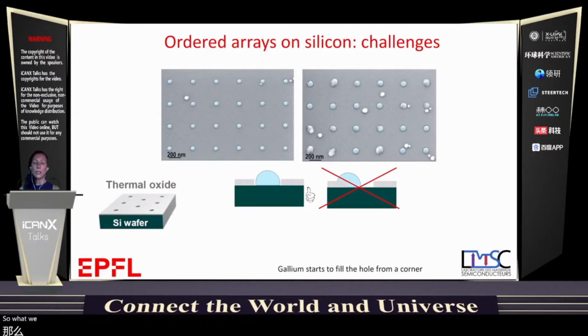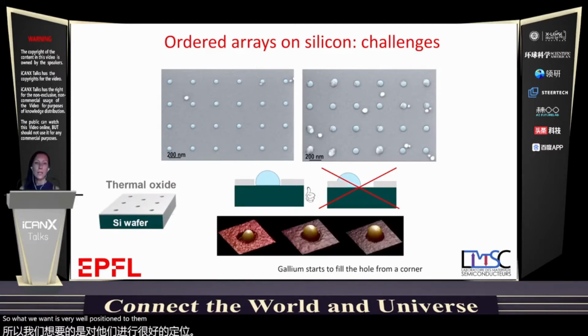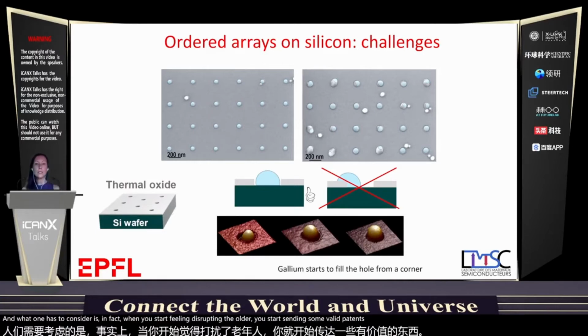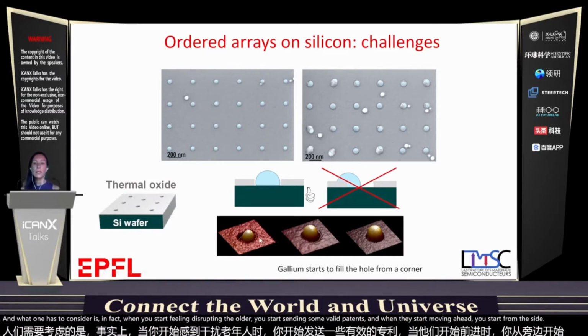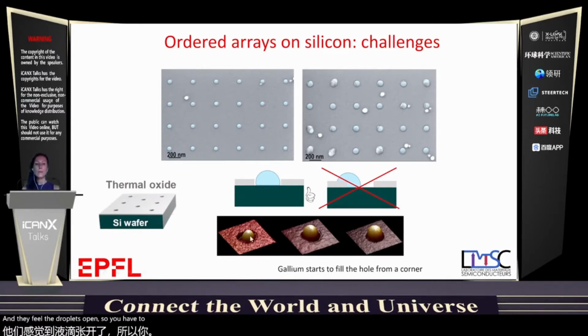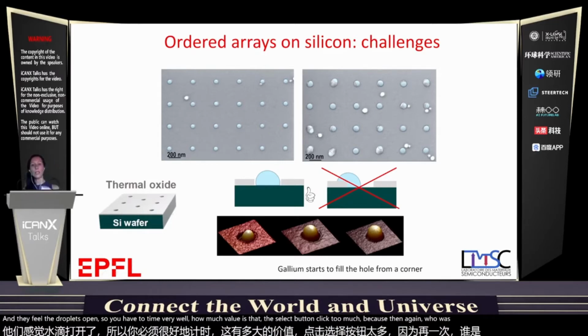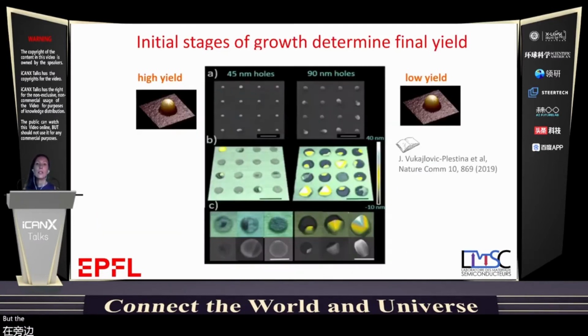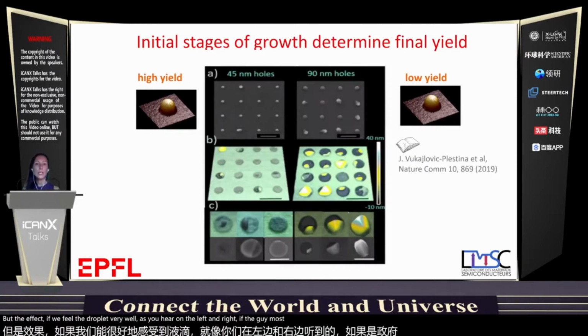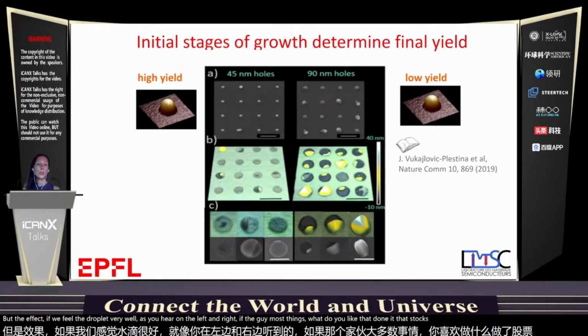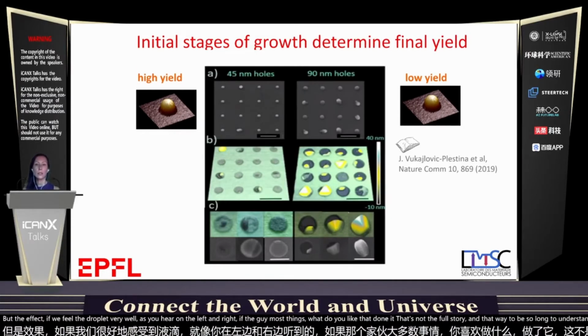So what we want is a very well positioned droplet. And what one has to consider is, when you start creating this droplet in the hole, you start sending some gallium atoms, and when they start growing, they start from the side, and they fill the droplet sideways. So you have to time very well how much gallium you send, so that you fill it, but don't fill it too much, because then again, you will start having the droplet going on the side. But in fact, even if we fill the droplet very well, there are more things. We realized that that's not the full story. And that's why it took us so long to understand the mechanisms.